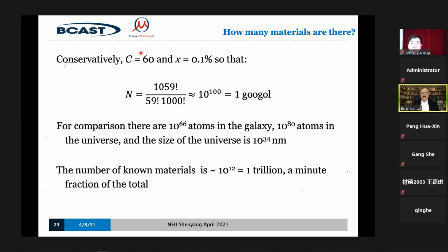And X, now how big is X? Well, we normally specify materials to at least 0.1% and sometimes 0.01%. If you look at the composition of a steel or a ceramic, that's the specification. A very poor quality metallurgical or ceramic material is specified to 1%. And of course, some materials like high strength steels, silicon or nickel superalloys are specified to parts per million. So again, conservatively, let's take X as 0.1%. In that case, that formula gives you the answer of 10 to the 100. The total number of alloys, if we have 60 starting materials and we can change the composition of each of those components by 0.1%, is 10 to the 100, which is a Googol.